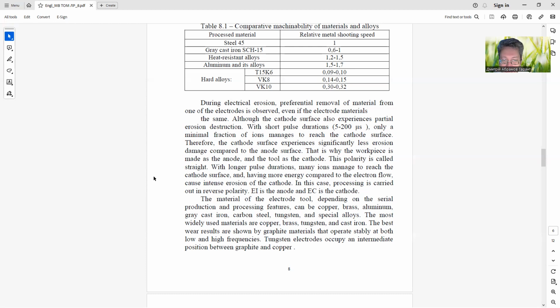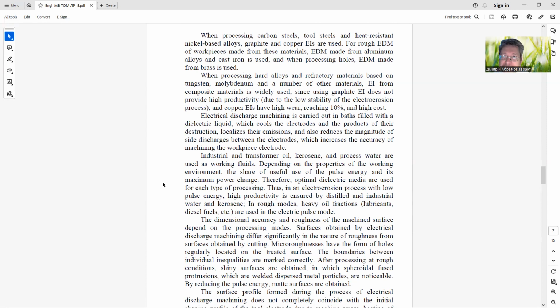The best wear results are shown by graphite materials that operate stably at both low and high frequencies. Tungsten electrodes occupy an intermediate position between graphite and copper. When processing carbon steel, tool steels and heat-resistant nickel-based alloys, graphite and copper EIs are used. For rough EDM of workpieces made from these materials, EIs made from aluminum alloys and cast iron are used, and when processing holes, EIs made from brass are used.